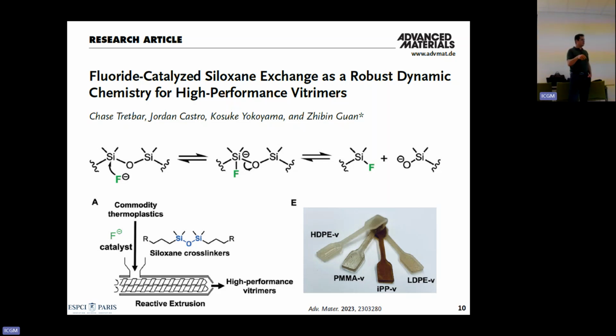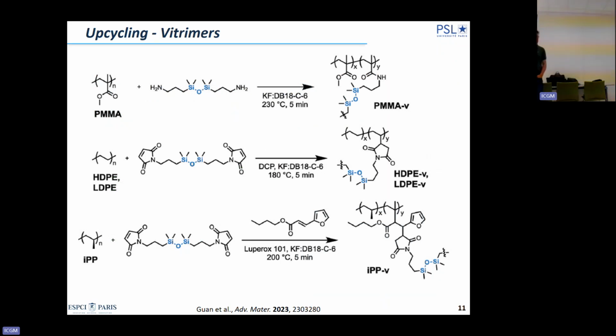And then potentially you can transform the polymer during processing into a vitrimer and see if you can create good interaction at the interface. So in this work, they prepared PMMA vitrimer using the amidification of the pendant ester, and this way they are crosslinking PMMA with this dynamic bond. They made a polyethylene vitrimer using reactive processing and a very similar approach with a bismaleimide.